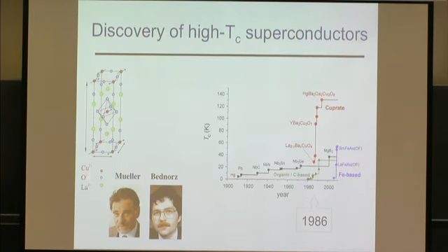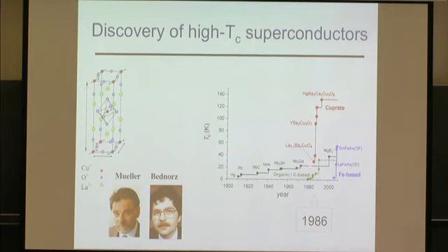In 1986, these two gentlemen discovered that the cuprates exhibit high-Tc superconductivity, over 30 Kelvin, and within a very short time, a few years, the Tc has been raised up to actually more than 140. Under pressure, its highest record is about 164, and it stays there. But this record, you see all these red dots, really sticks out compared to all the other superconductors, including the recently discovered iron pnictide superconductors, where the highest Tc is 55 Kelvin.